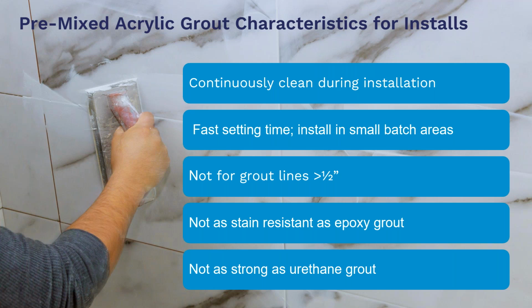There are characteristics to a premixed acrylic grout for installation. You need to continuously clean it during installation. That allows you to keep the grout haze off of the tile. It's fast setting in time, so you want to make sure it's installed in small batch areas. Think no more than an arm's length. It's not for grout lines that are greater than 1/2 of an inch.